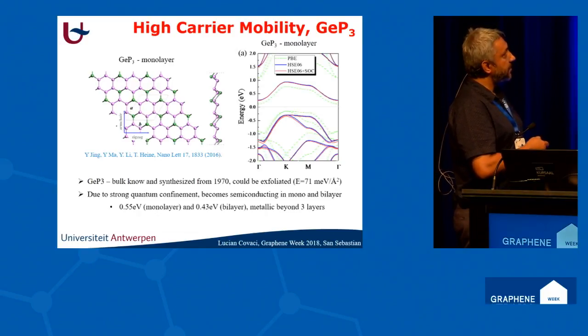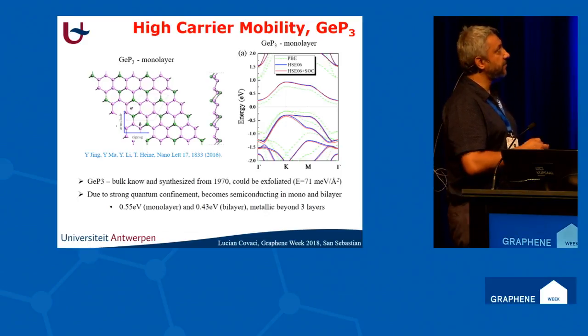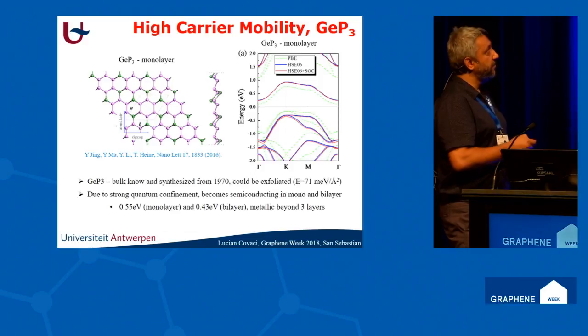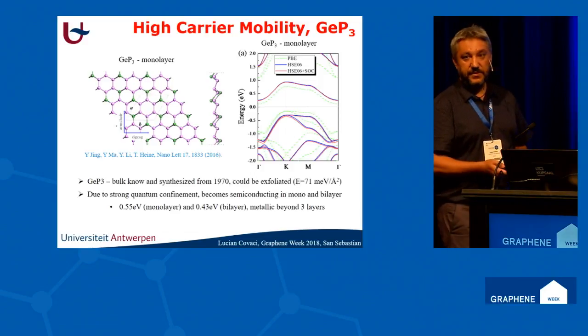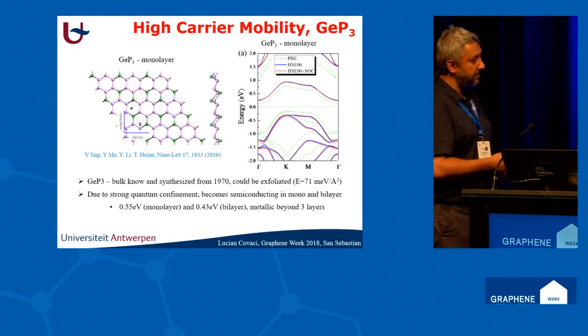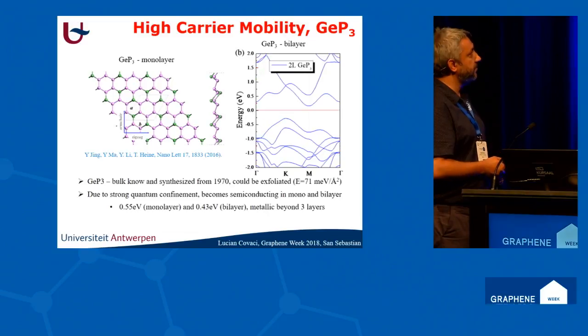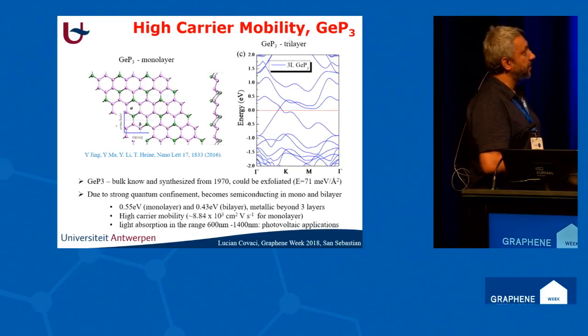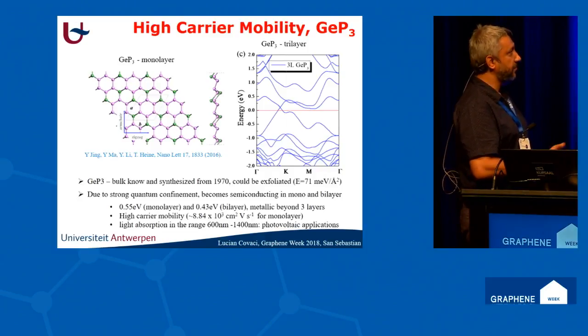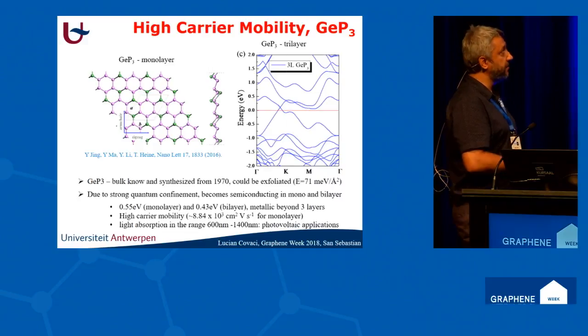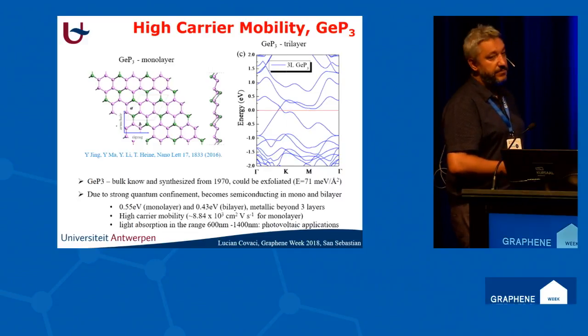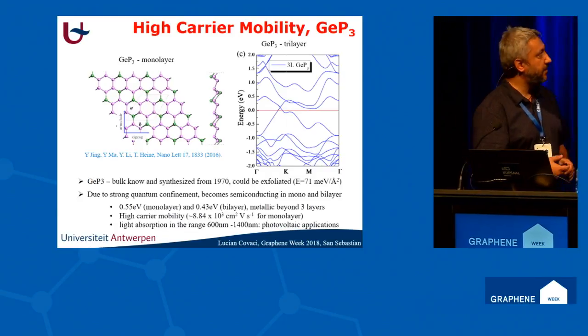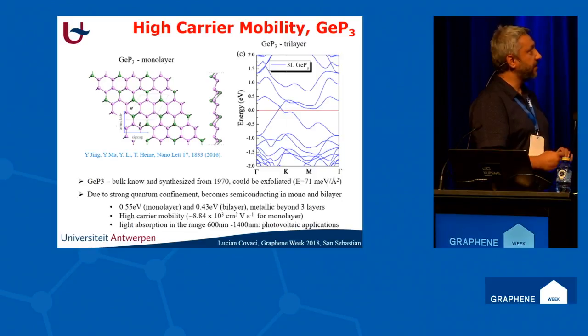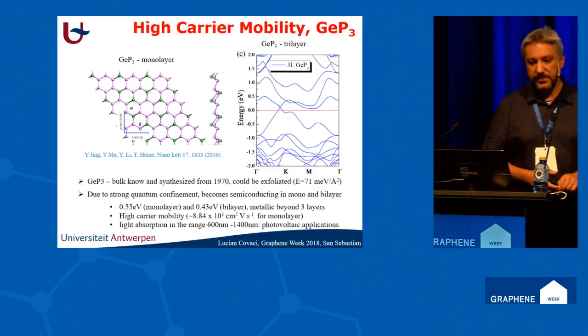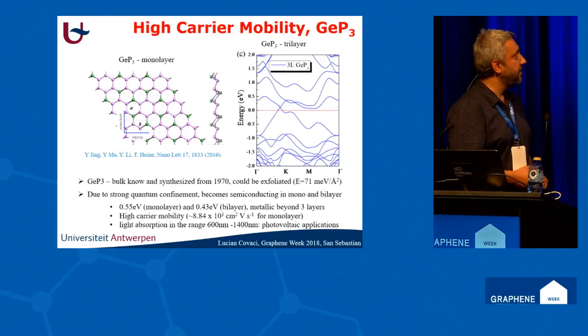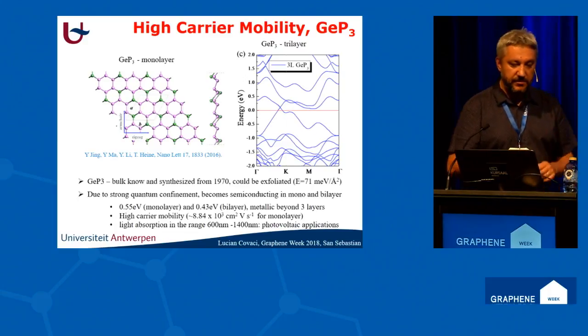And so the bulk is metallic, but due to strong confinement, as you thin it down to mono or bilayer, you start developing a gap. The values of the gap are very interesting for optical applications, because the response is in the visible range. So this should be a very interesting material for photovoltaic applications. But also, interestingly, they show high carrier mobility for the monolayer. So you can combine this high carrier mobility with small gaps, which in principle you have also for phosphorene, but as we know, it is highly reactive unless you encapsulate it. So this could be an alternative material.